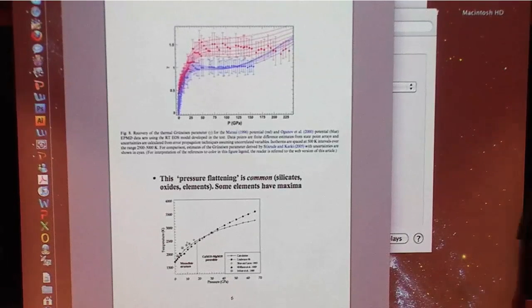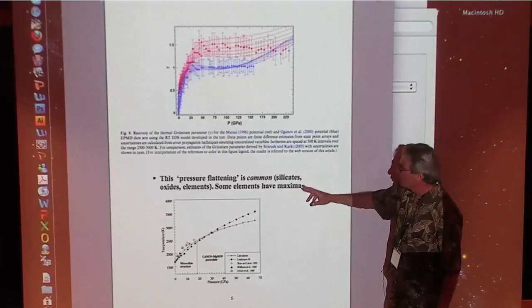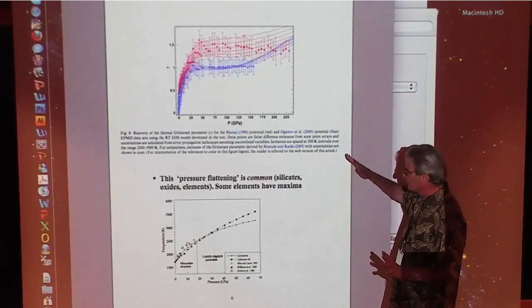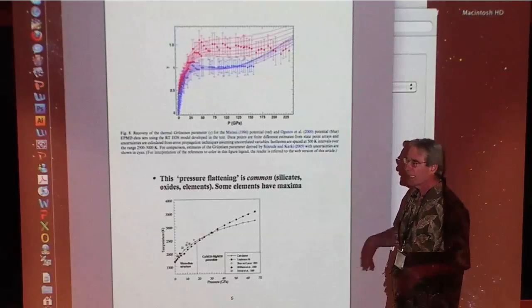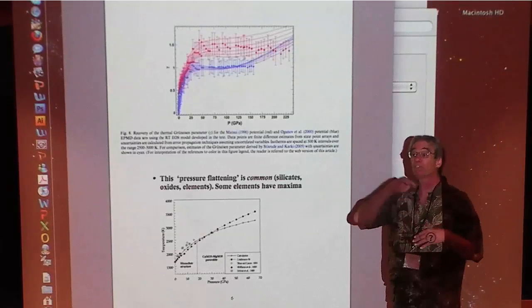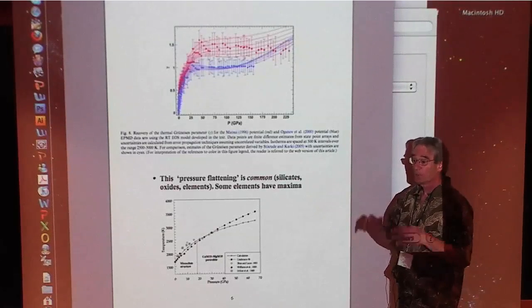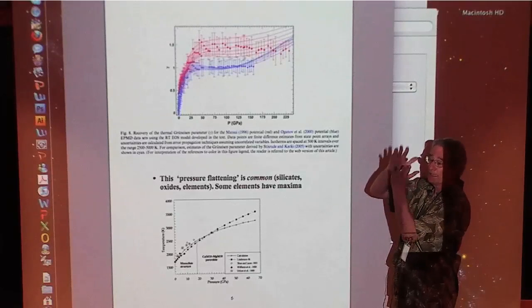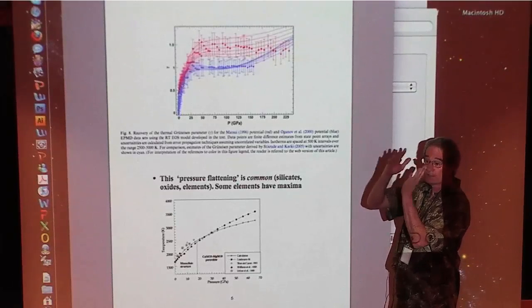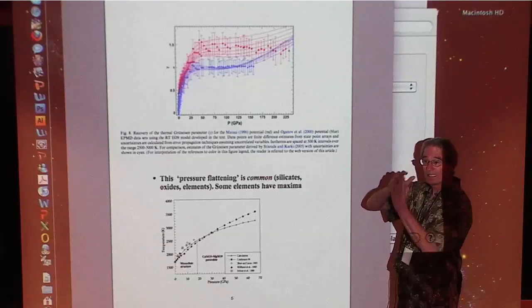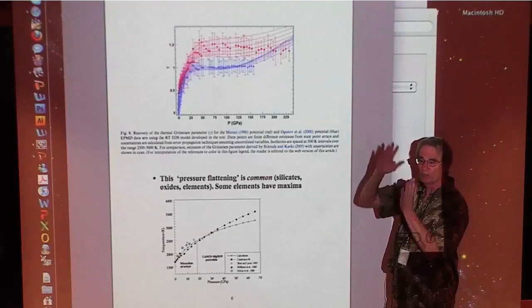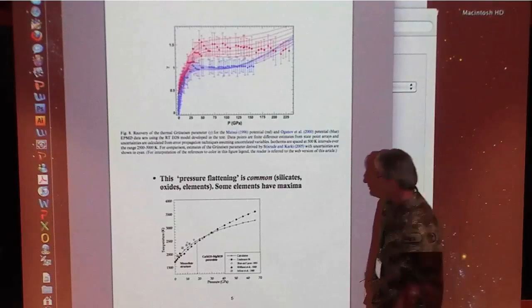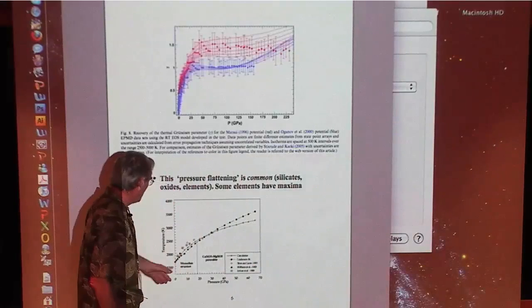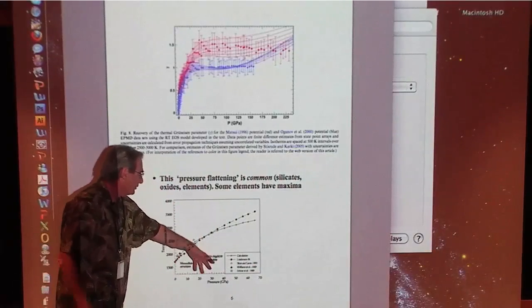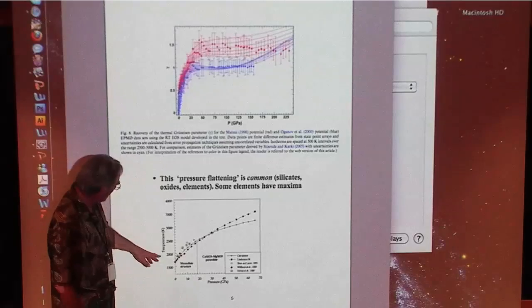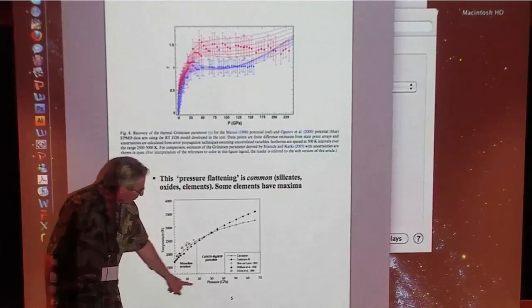But what I really want to leave you with is some melting curves for some silicates and some other compounds, and show you that they really do flatten with depth. Meaning that the Clapeyron slope and the adiabat are becoming more nearly parallel. And I think you can get a big region with low degrees of melt if they're touching. So here is, God knows what this is. Okay, this is basically calcium perovskite, and here's a melting curve. This is temperature, this is pressure.